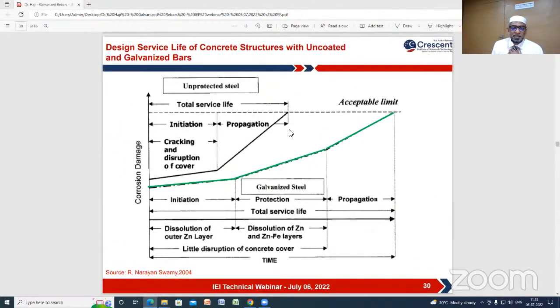This is again the same concept. In the uncoated rebar, once corrosion initiates, then propagation is fast. In the galvanized rebars, corrosion initiation will take a long time. Even after the corrosion initiation, zinc only corrodes. So up to here, it is a protection stage. Zinc corrodes and protects the steel. From here only, real steel corrosion is happening. So you can imagine that from here to here, there is so much horizontal length, and that will give the trouble-free service life.